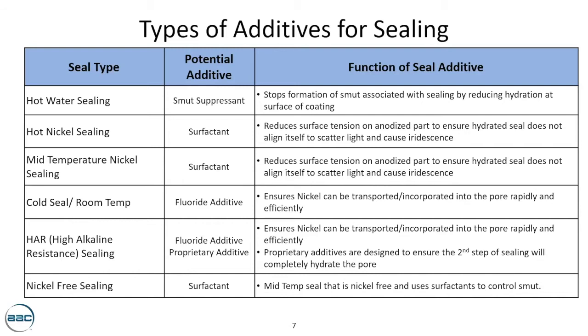High alkaline resistance. So the primary step in this starts with a cold seal. So there's obviously the fluoride additive that's important. And then in the second step, there's a proprietary additive that's used. Certain companies provide different additives, but essentially there's a second step additive that you can use to ensure that you're getting the right second step to meet this 13.5 pH requirement.